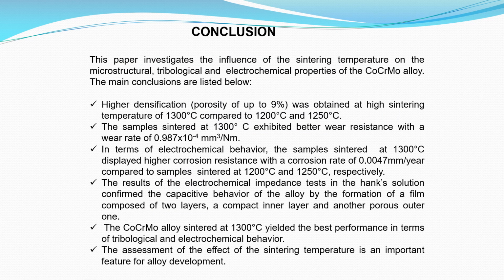The main conclusions are as follows. Higher densification was obtained at the highest sintering temperature of 1300 Celsius degrees. Also, the samples sintered at this temperature exhibited better wear resistance.